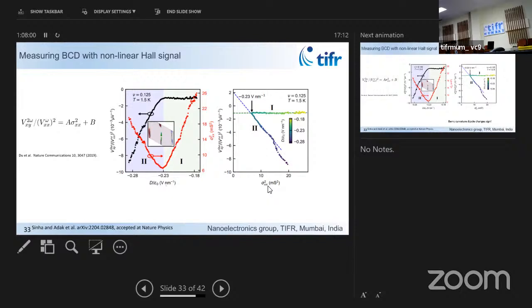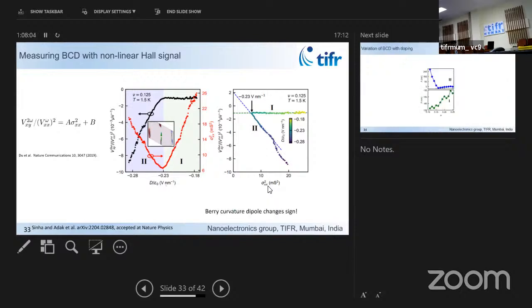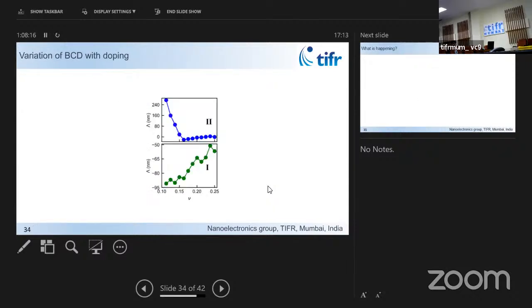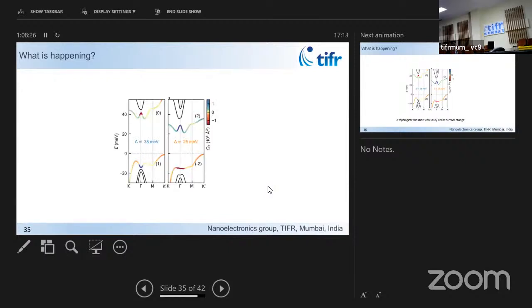Okay, now that is, as I will show you in the next slide, basically the Berry curvature dipole changing its sign, and this point is actually a point where the topology of the system changes, the Chern number of the system changes. So we skip this. We characterize how the Berry curvature dipole is as a function of doping. What is happening, and this is maybe the last slide because I'm running out of time, is that as you change the electric field, these flat bands will touch the remote bands, and the Berry curvature flips sign. And after that, the valley Chern number of the system undergoes a change, and that gets reflected in the Berry curvature dipole.